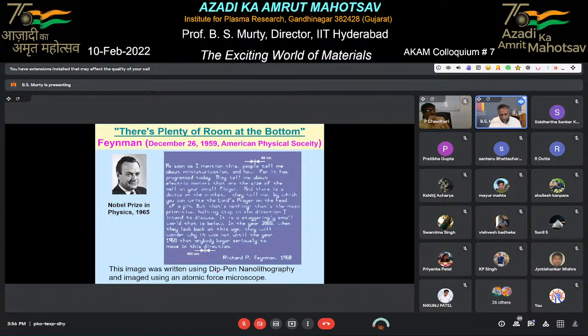What they do is they use a technique called dip pen nanolithography. What you see here, every white letter on a blue background is all written by this kind of nanolithography technique, where the distance between these arrows is about 60 nanometers. That means each letter is of the order of 50 to 60 nanometers. That kind of letters, it is possible. But then how do I see it? I need a microscope to see it. It is like a miniaturized writing with a pen, very sharp pen. And I need to use some microscopes such as AFM to see them.